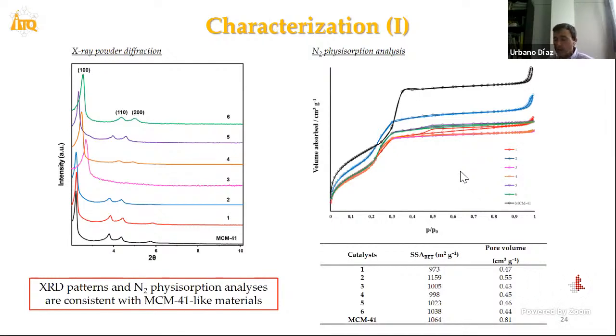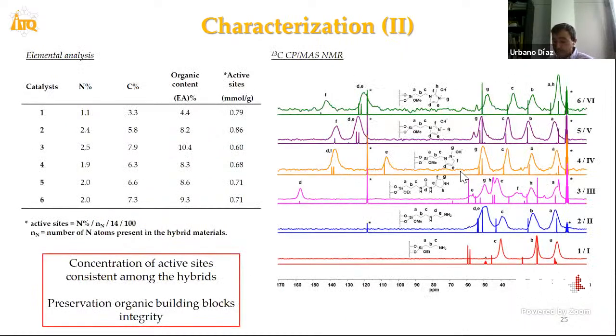of these hybrid materials. The characterization of the solids confirmed from XRD patterns the mesoporous character of these materials, with different pore size in the hybrid materials finally obtained. This is confirmed also from textural properties. In all cases, type 4 isotherms are obtained with very elevated surface area and pore volume. From elemental analysis and estimation of organic content, it was concluded that effectively the concentration of active base sites was consistent among the different hybrid materials.